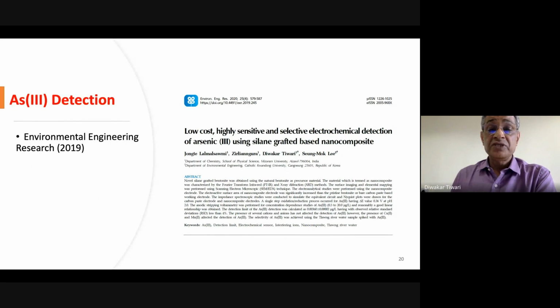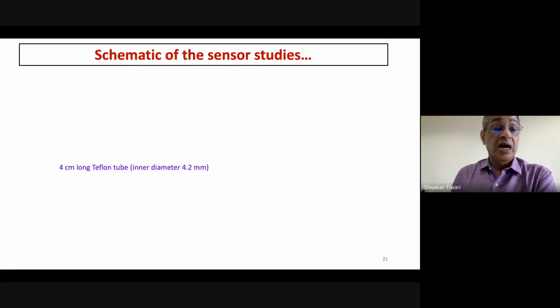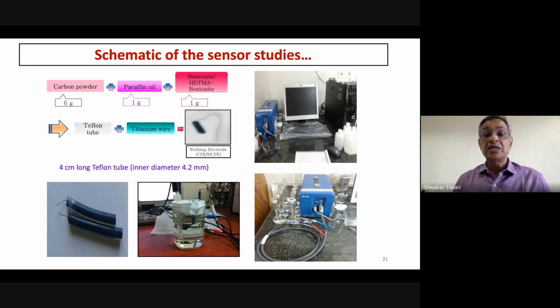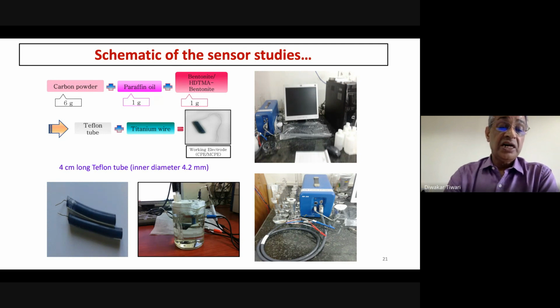So this is one of the papers which was published in EER. This is the schematic of the sensor studies. As I mentioned, the fabrication of the electrode was one of the aspects that we wanted to do. For that, we used the carbon paste electrode. Here is the Teflon tube. The Teflon tube was 4 centimeters long. In that, the paste which we made with our material, along with carbon powder and paraffin oil, to make a good paste. This paste has been packed into this Teflon tube, and a titanium wire has been introduced there to make the electrical connectivity.